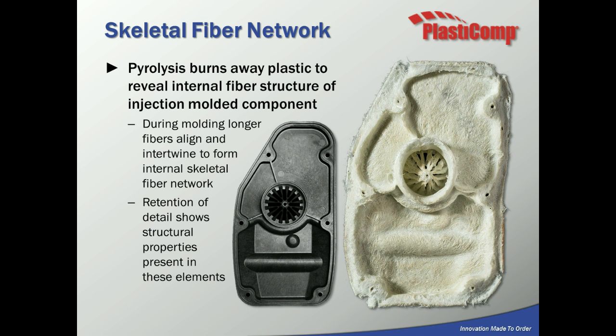This slide is my favorite slide because it gives a visual representation of why long fiber materials have the properties that they do. On the left, we have the black part, which is a molded part of a nylon 6/6 with long glass, likely 50%, and the part on the right is a burn-off of that part, where we've essentially taken the resin and burned it away. And what you can see is left is a skeletal matrix. We've got some areas where there's high fiber orientation, and then we have other areas where those fibers are intertwined with each other. And it's this skeletal matrix that gives the high strength, stiffness, but also impact resistance.